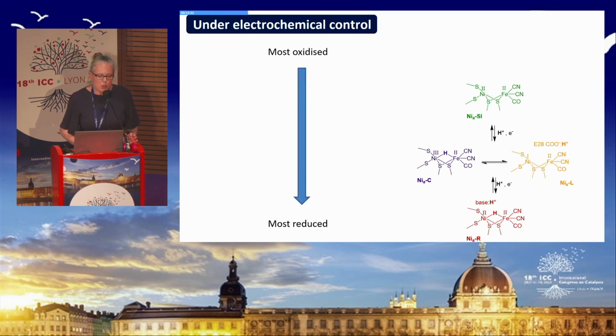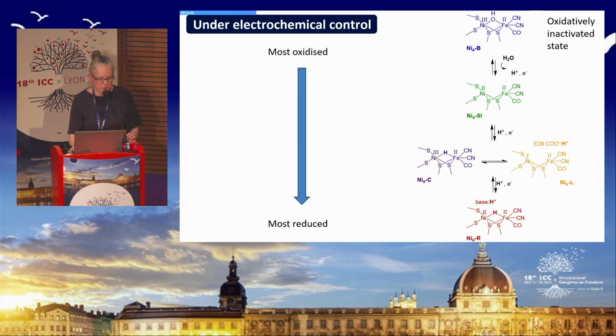Great. So we can also think about moving through or navigating through these different states under electrochemical control, because each of these steps in the catalytic cycle is simply transfer of protons and electrons. And so this is work that's been done on a number of hydrogenase enzymes in solution where an electrochemical potential has been applied, and you can use that to navigate from the most oxidized down to the most reduced state of the active site. We've been able to do that under catalytic control on an electrode surface, handling the hydrogenase as an electrocatalyst. And in that way, we can use electrochemistry as a very valuable tool to control the state of the enzyme during catalysis and during spectroscopic measurements.